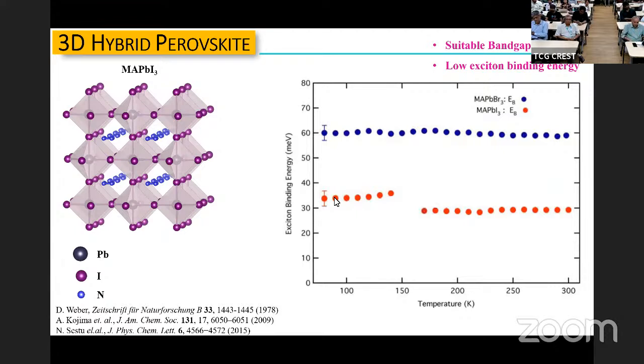For the iodine compound, you can see this break is because there's a phase transition, it is in the order of 30-35 milli-electron volt. The bromine compound is around 60 milli-electron volt, which are comparable to the thermal energy scale. This is about twice the thermal energy scale. So e to the power minus half is still not a very small quantity, and you'll be able to drive the photovoltaic cell even with an excitonic binding energy of that.